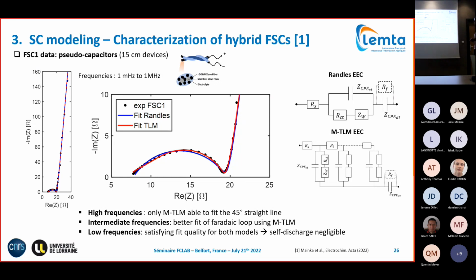At intermediate frequency, the spectrum is characterized by a depressed semicircle, since the pore space has an impact on ion diffusion, and at the lower frequency, you have a steep line associated with purely capacitive EDL charge storage. So what you see is that at the highest frequencies, the Randles circuit is unable to take this into account. And this is logical because, I remember, the Randles circuit is based on an interfacial electrode, so by definition it cannot take into account this 45 degree slope. Whereas our modified TLM yields a satisfying fit quality.